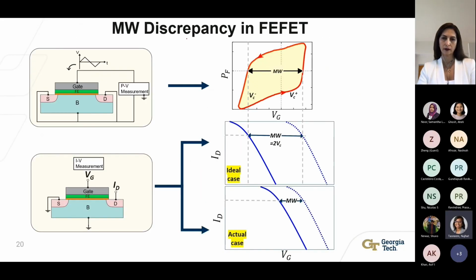So in the next slide, I tried to depict the memory window discrepancy problem in FeFET schematically. If we have an FeFET and we try to measure the charge-voltage characteristics of the gate capacitor of the FeFET by applying a voltage at its gate terminal and grounding the shorted source, body and drain, we see a hysteretic PV loop like this. Now, if there was proper electrostatic coupling between all the layers in the FeFET's gate stack, then ideally, the memory window that we get from the ID-VG curve of the FeFET should be equal to the memory window that we get from the PV loop.